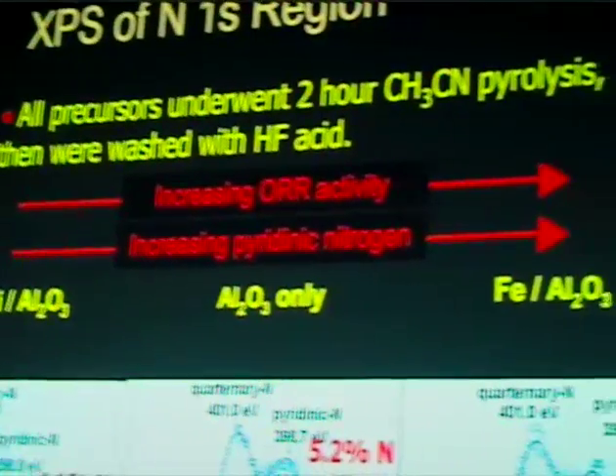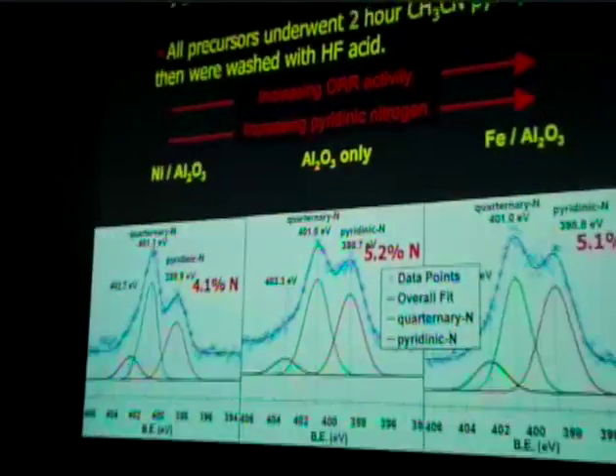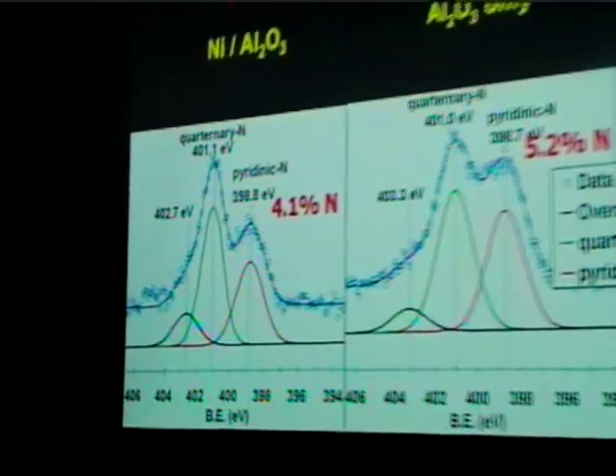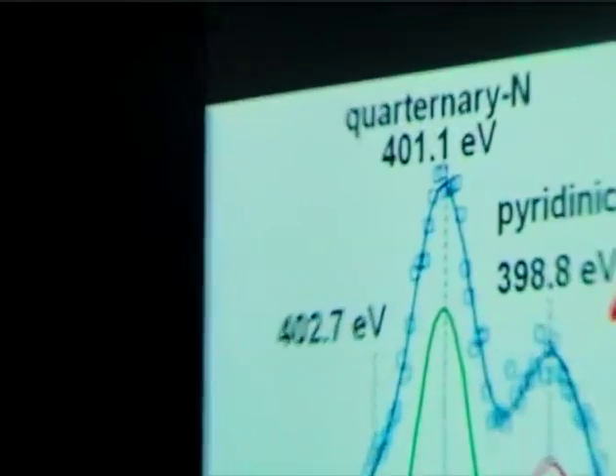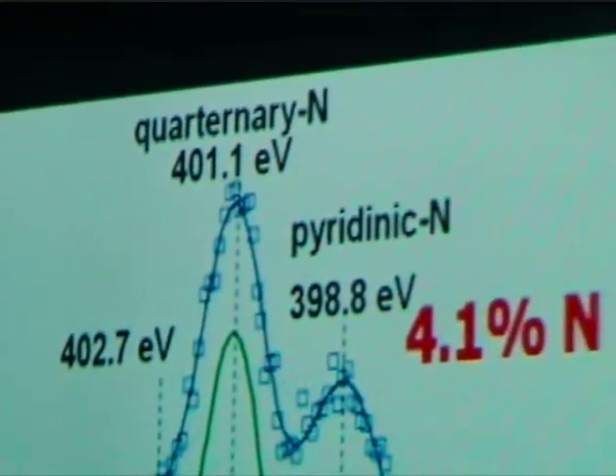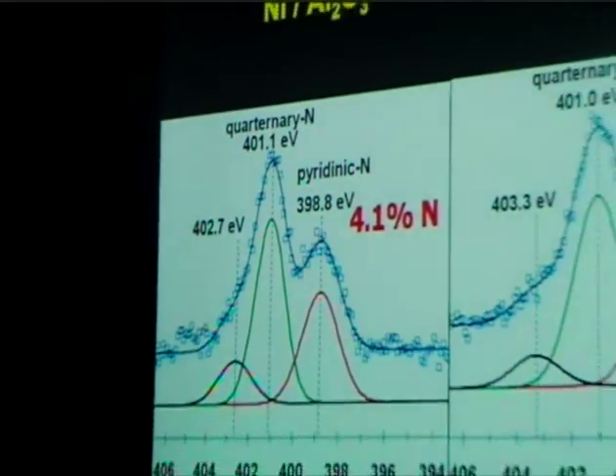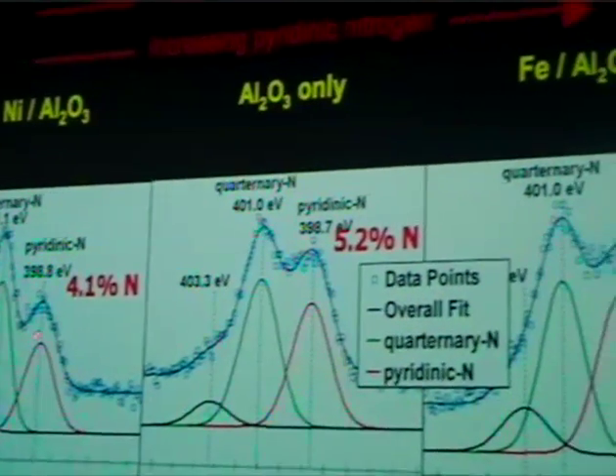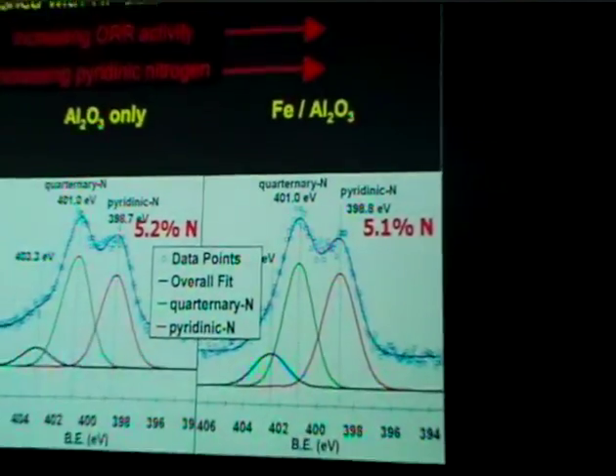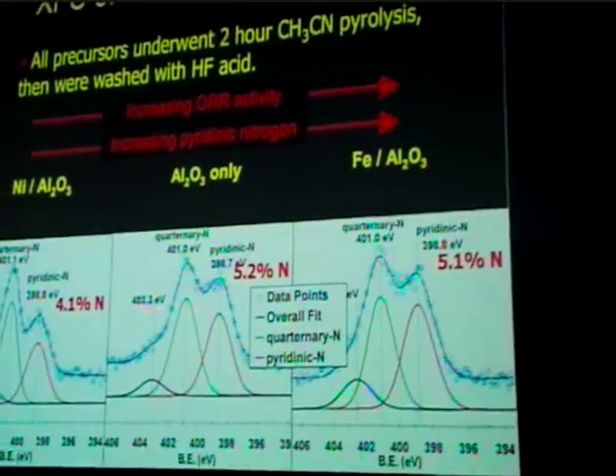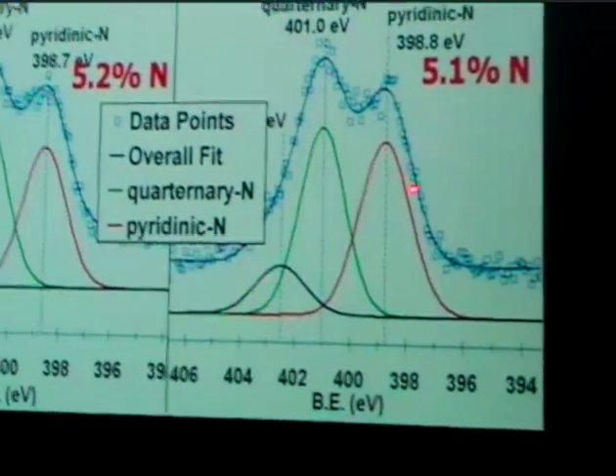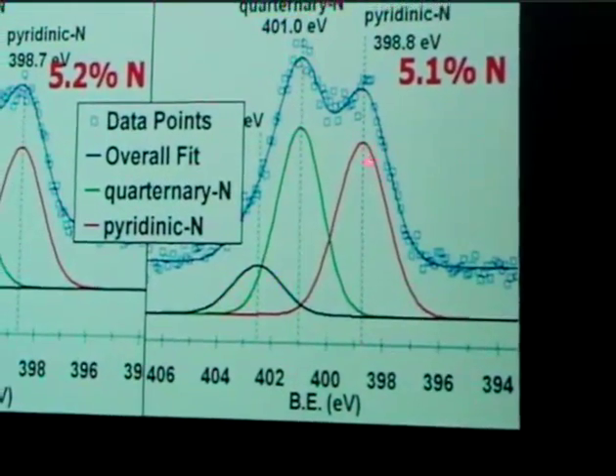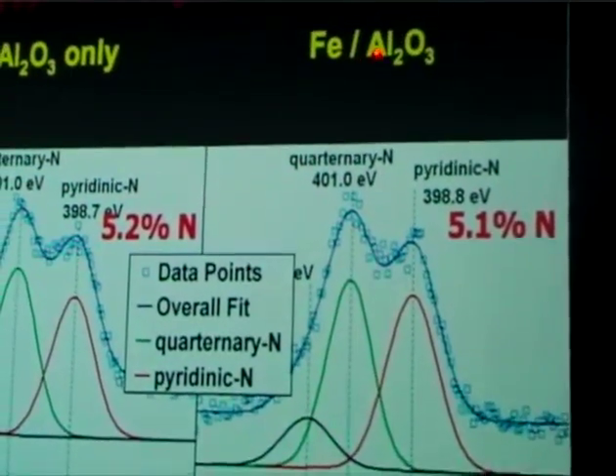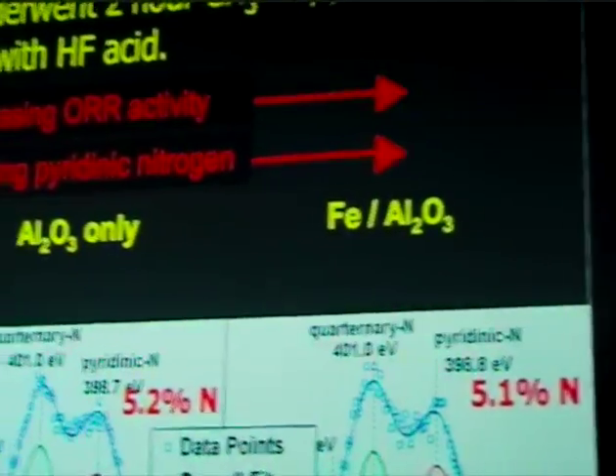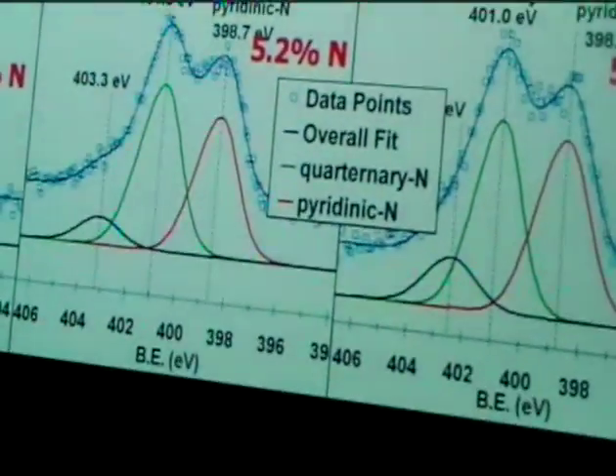oxygen reduction reaction activity and how it correlates with the nitrogen content, and especially the pyridinic nitrogen content, we see a very interesting behavior. If we look at, again, deconvoluting the pyridinic nitrogen here, as we go in this direction, we clearly see that the pyridinic nitrogen signal is growing. And this is also the direction where we are getting the increased oxygen reduction reaction activity.